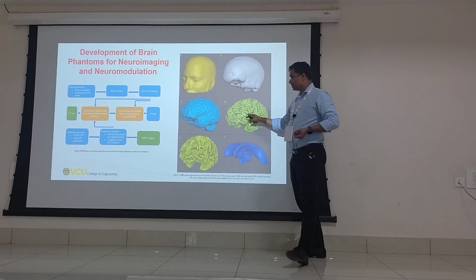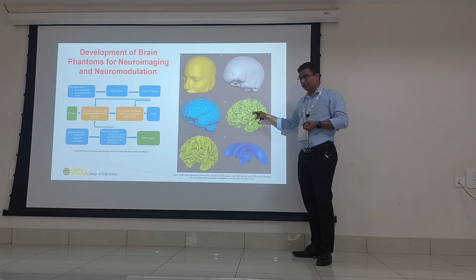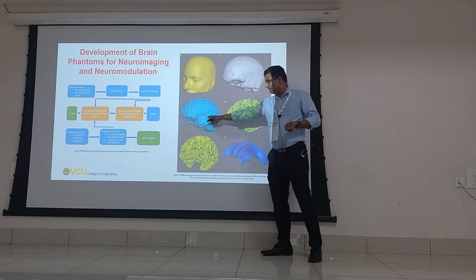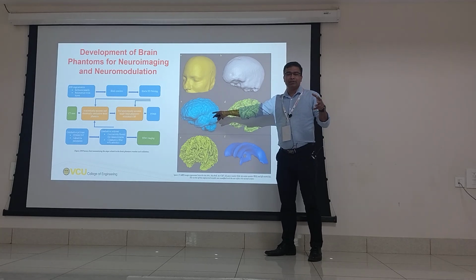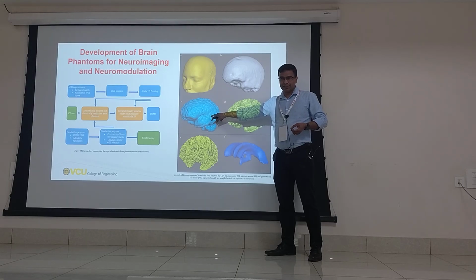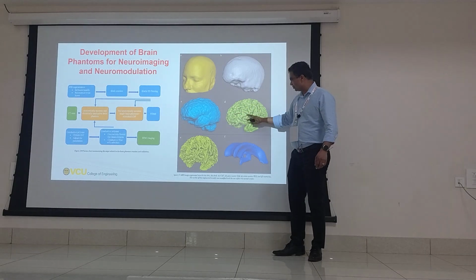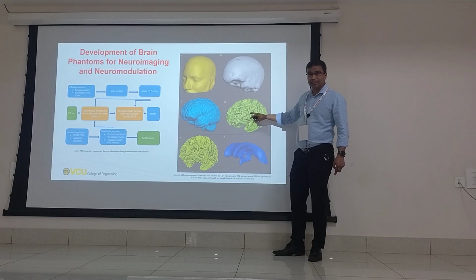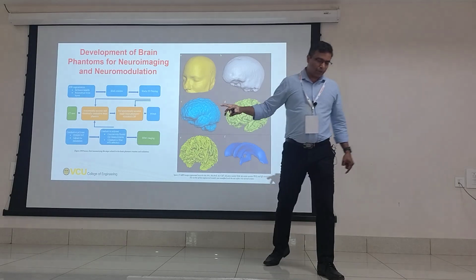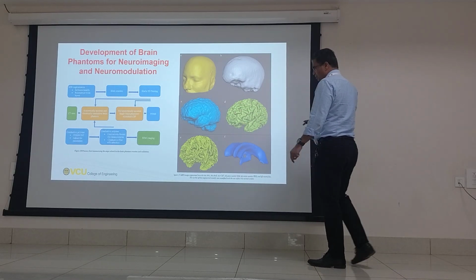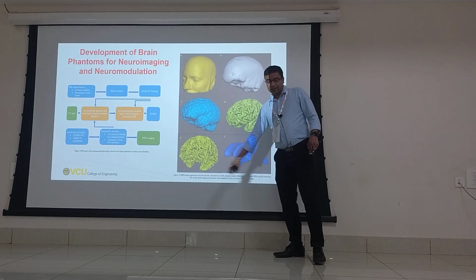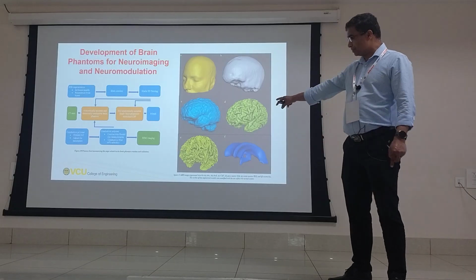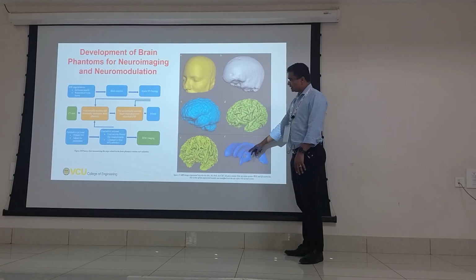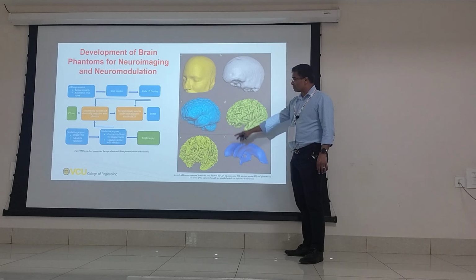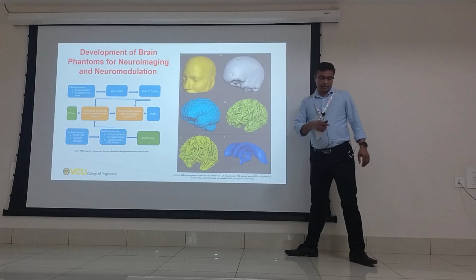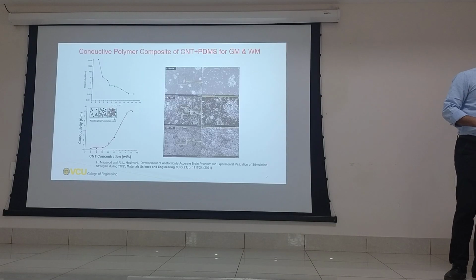So that is CSF. Gray matter has a certain electrical conductivity. We need to replicate it, which is not that hard, because by changing the salt concentration, you can get the electric conductivity matching that of human CSF. Here, this is gray matter. It has electrical conductivity of about, I think, 0.28 Siemens per meter. And this one is something like 0.33 Siemens per meter. Then these are ventricles. Ventricles are special regions in the brain which are also filled with CSF. Okay? So all the properties of these regions should be replicated.